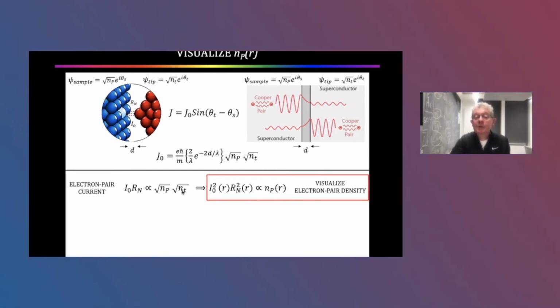And we assume that the gap in the tip, the number density in the tip, is constant. So what that means is if I measure the Josephson critical current squared, and suppose I keep the normal resistance constant, then I get a measure at that location of the density of pairs in the sample. This concept has been around for decades to visualize the condensed electron pairs rather than the single electron quasiparticles.